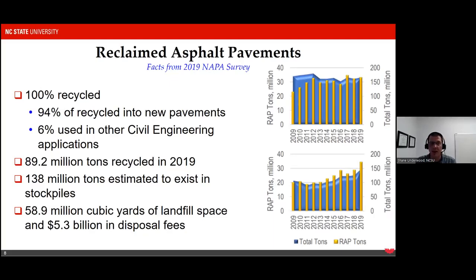A portion of those 94% recycled rates incorporate using RAP into aggregate bases or using them as shoulder repair, but the vast majority are recycled back into new asphalt concrete pavements to create a circular use of those materials. In 2019, the last year that data was available on these recycled rates, we recycled in our country about 89.2 million tons. And I will emphasize that those are US tons, not metric tons. So less in terms of metric tons, but nearly 89 million tons of recycled material.